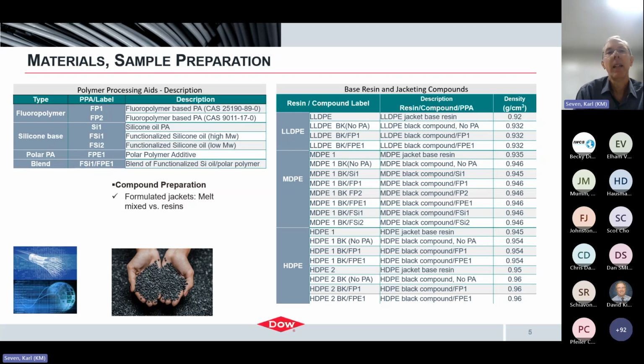The table on the right has a lot of information, but basically what I'm showing here is that we mostly concentrated on medium density jacketing compounds. That's where most of the studies that I'll show here are. So this is looking at how these different processing aids perform within the medium density jacket compound. But we also expanded out to linear low as well as high density jacketing compounds. So basically, these are just the different combinations of jacketing compounds with various non-PFA based processing aids.